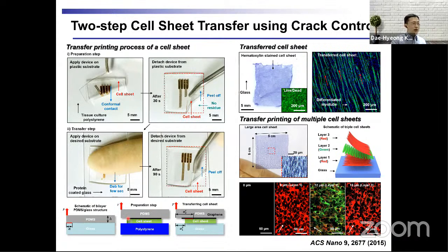So in our case, we laminated a very thin graphene layer on the PDMS surface. Since the graphene layer is very thin, it doesn't affect the soft nature of the PDMS stamp. And graphene has very good adhesion with cells, such as cardiomyocytes or mesenchymal stem cells, so we could culture the cell sheet on the graphene layer. In addition, we patterned the graphene layer as a line base for the purpose of alignment of the cell sheet. This is a magnified view of the cultured cell sheet, which shows good alignment of molecules.